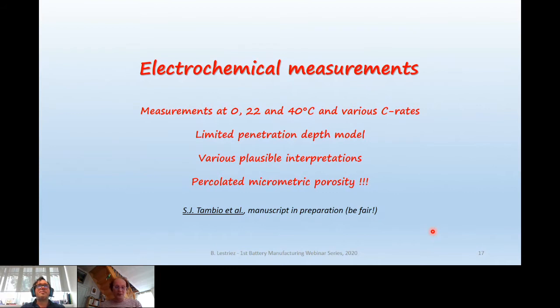So now let's inject these interpretations into the electrochemical data. We have made measurements at 0, 22, and 40 degrees C at various C rates, and we have analyzed our results with the limited penetration depth model. And you will see that again, we end with the conclusion that what is leading the game is very likely the percolated micrometric porosity.